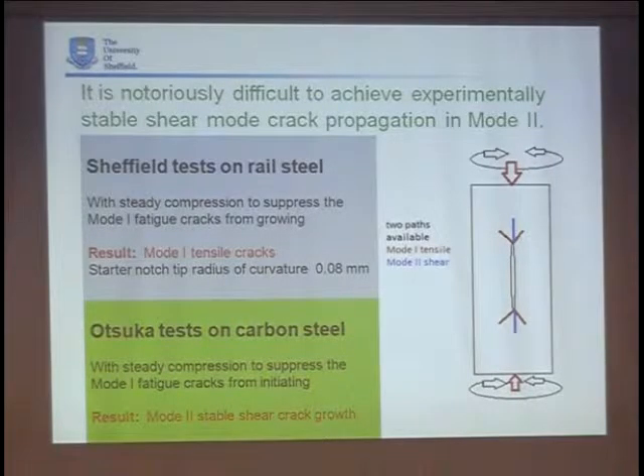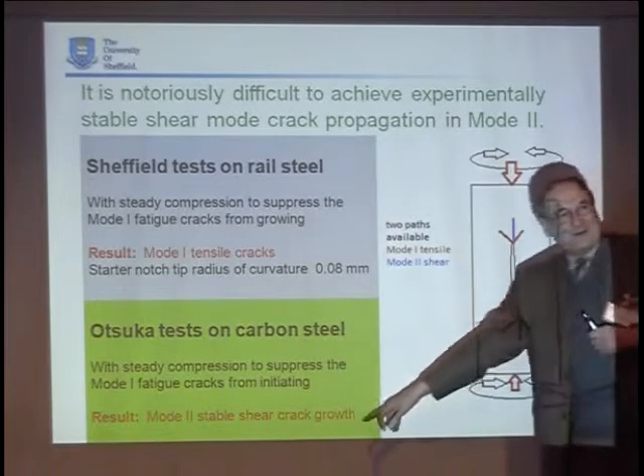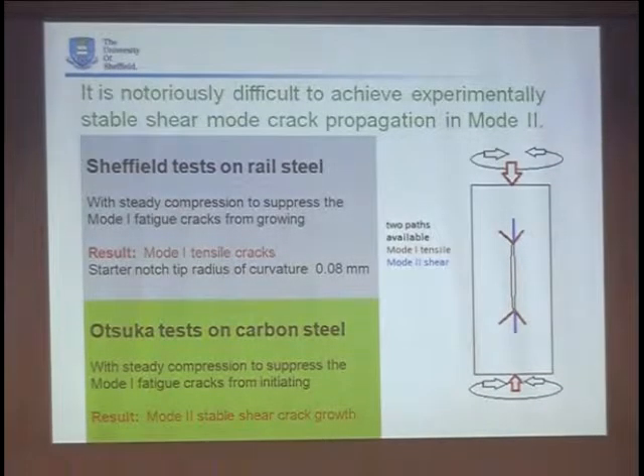So we got our specimens ready, got the machine going, and however large a compressive stress we put on, the cracks always grew in the red direction as Mode 1, and we failed completely. Otsuka in Japan used asymmetric 4-point bending and some clamps to put in the compression, and he got some nice Mode 2 stable shear crack growth. But apparently the same test, with different specimen geometries. Why did we fail when he succeeded? That's really what this talk's about.